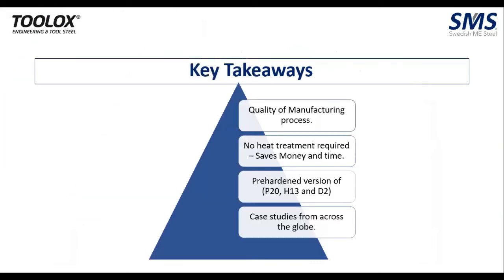So we come to the end of our webinar, wherein if you see the key takeaways of this, you can say that the quality of the manufacturing process that we have produced, as we said, it's modern manufacturing techniques being used, and you get it in 45 HRC ESR property material. As we said, it is delivered at 45 HRC, and though there is no heat treatment required, it saves money and time. It's in pre-hardened version not only for your P20, it has worked across the globe as a pre-hardened version of your H13, H11, as well as your D2. That is a pre-hardened version for both your hot working as well as your cold working tool steels. So we also saw case studies from across the globe, and we'll finish it off with one more video of machining,